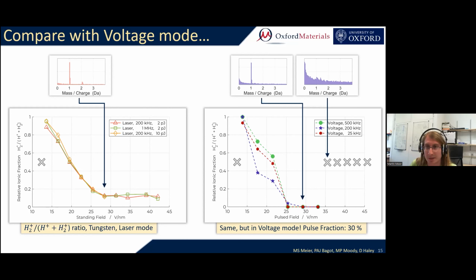our laser experiment. So number one, the laser is doing something to the experiment that is causing a supply of contaminant hydrogen onto our tip, even under conditions where there's no contaminant hydrogen in the tip in voltage mode. Or number two, the laser is doing something to the experiment that is causing the on-pulse evaporation of contaminant hydrogen, even under conditions where all of the evaporation is happening off-pulse in voltage mode.